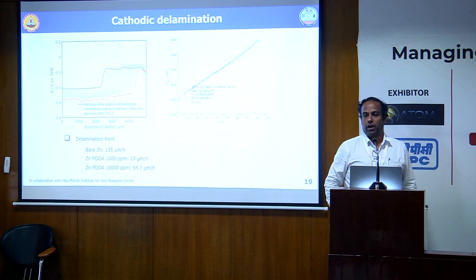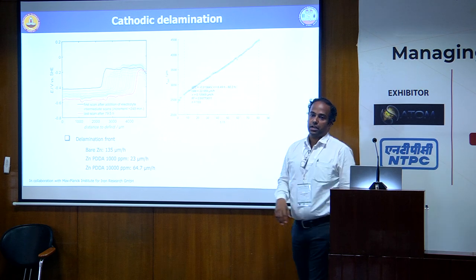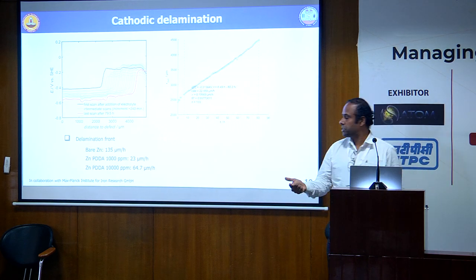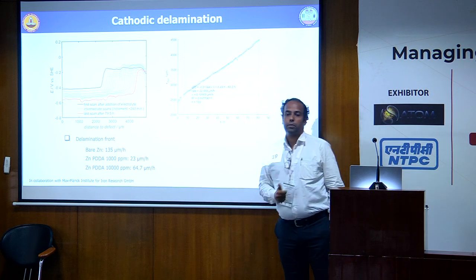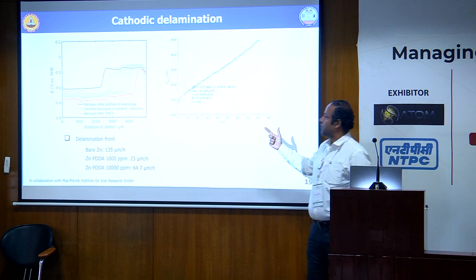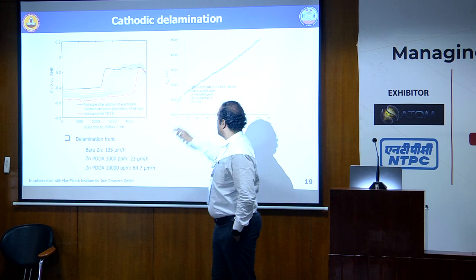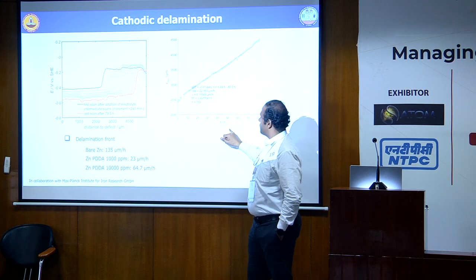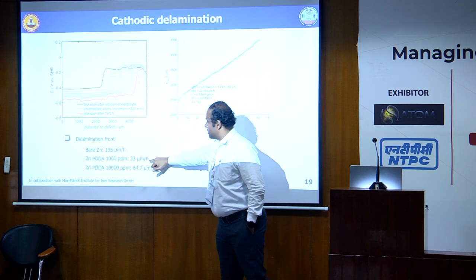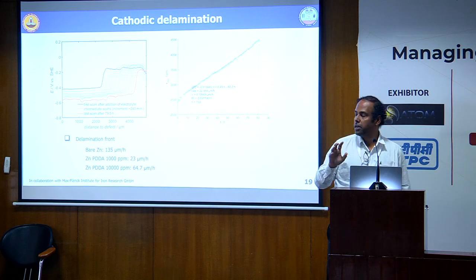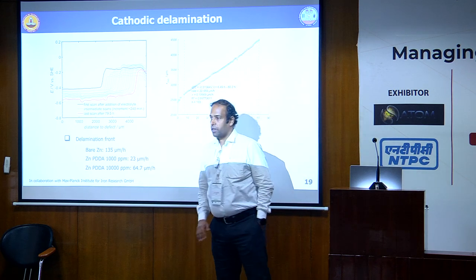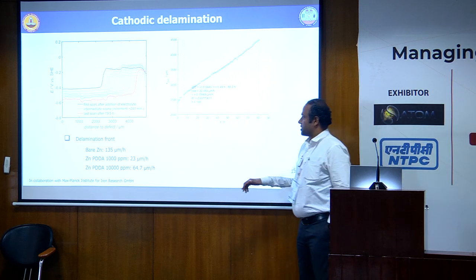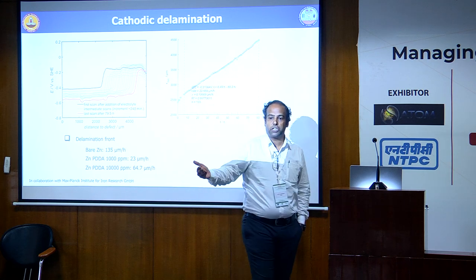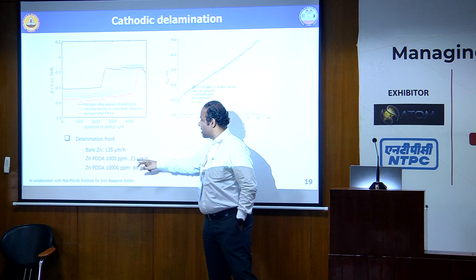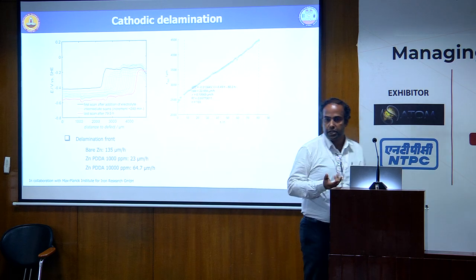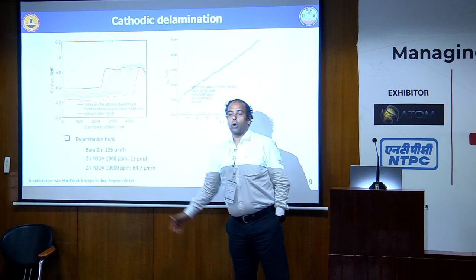What we did, we tried it for our zinc coating, which is dispersed with these particles. We compared bare zinc, zinc with 1,000 ppm of these particles, and with 10,000 ppm of particles. I've given you only a figure for 1,000 ppm, where we see the delamination rate, plotted between distance and time. Zinc with PDDA at 1,000 ppm dispersed gives you a value of 23 micrometers per hour, which suggests that for your bare zinc coating, the progression of corrosion is much faster at 135 micrometers per hour. The optimum concentration would be 1,000 ppm of PDDA dispersed, which gives you close to 5 times lower than what you expect.